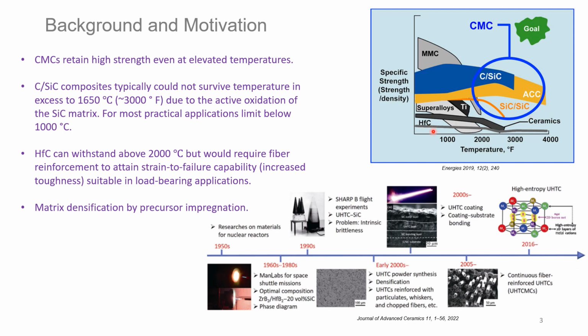Now, monolithic hafnium carbide may survive over 2000 degrees C. However, they are susceptible to catastrophic failure during their services. Now, the goal is to achieve high specific strength at elevated temperature, which is shown in this region here. And one solution could be to include ultra-high temperature ceramics or ceramic matrix into the fiber preform.